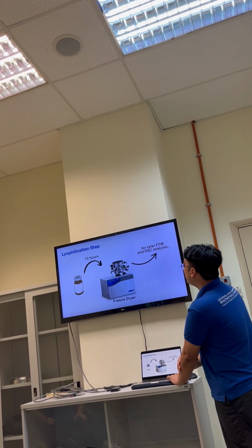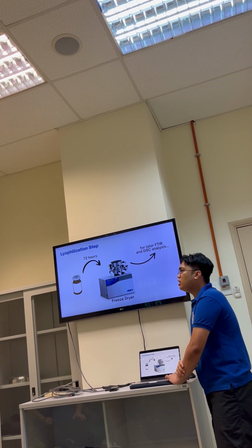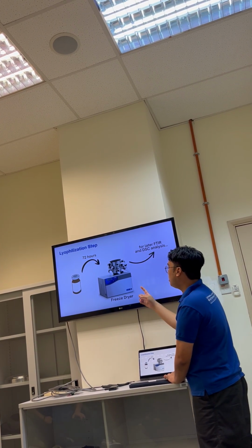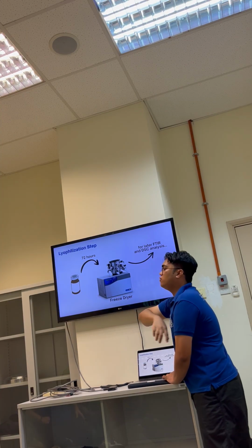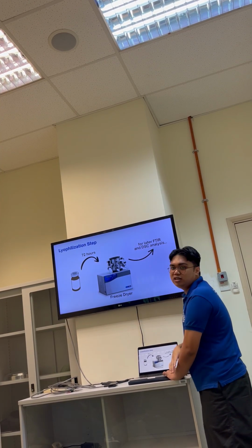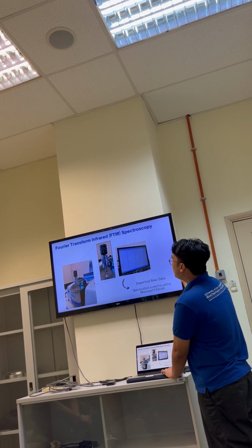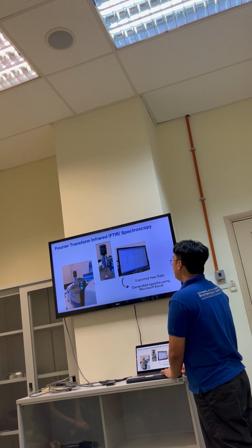Lyophilization step would be important for the later FTIR and DSC analysis. Of course, we need them in a dry state. So for 72 hours, the NLC solutions subject for further FTIR and DSC analysis was placed in the freeze dryer for 72 hours. Finally, we get the FTIR spectra.